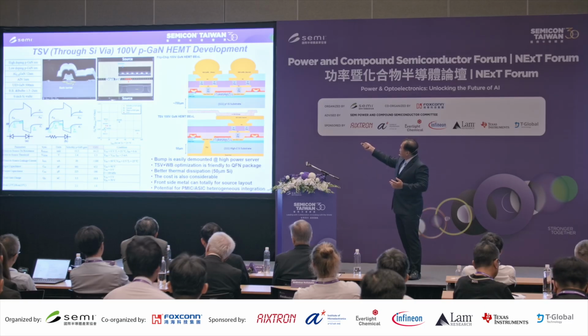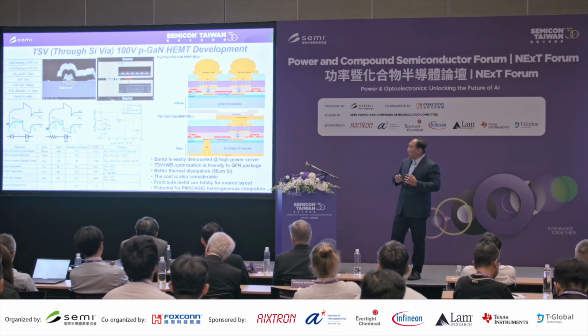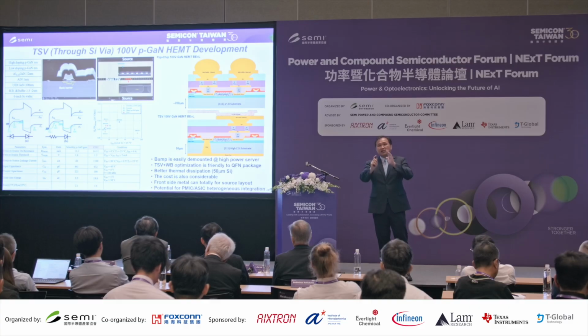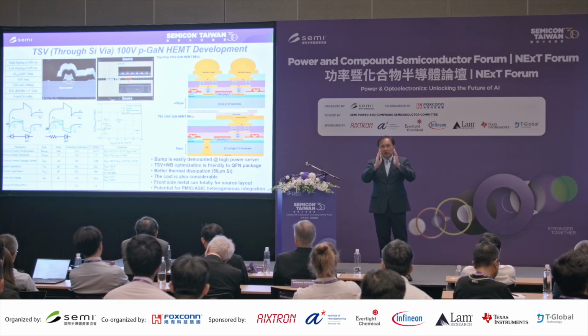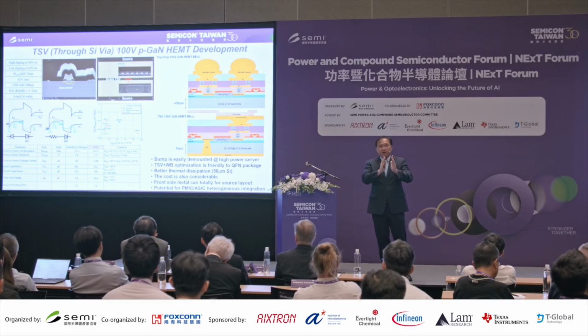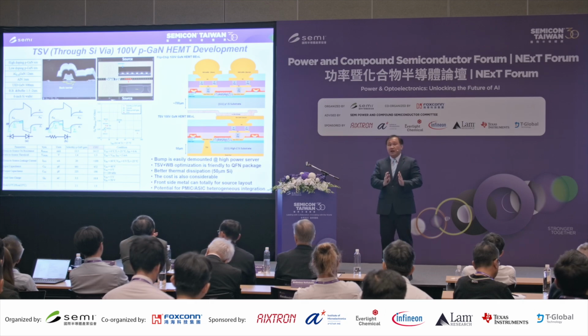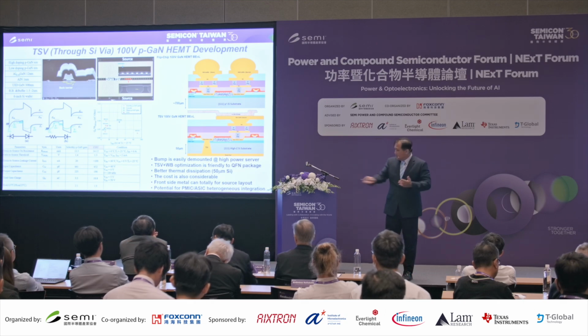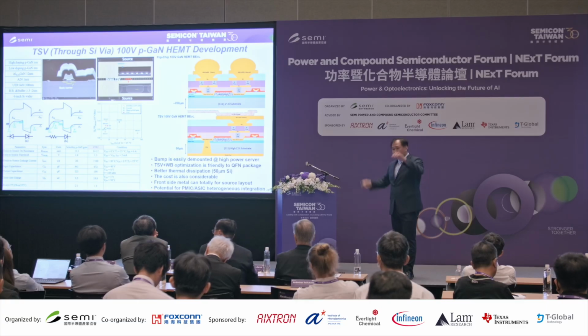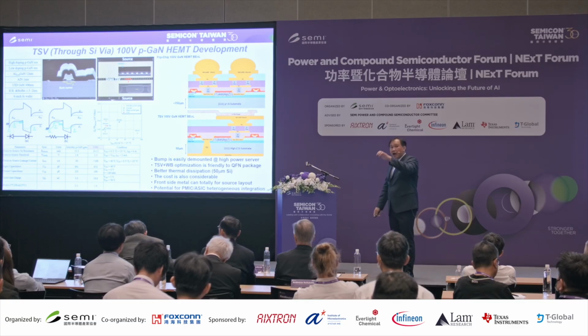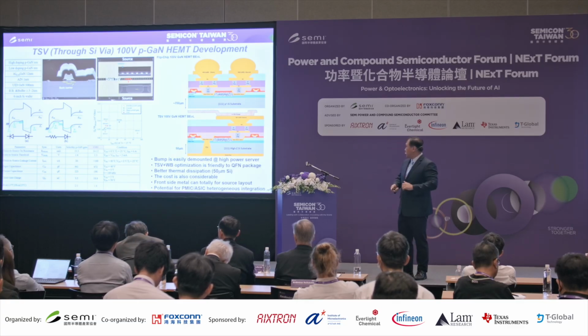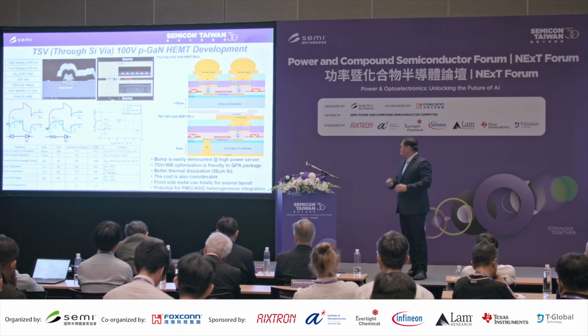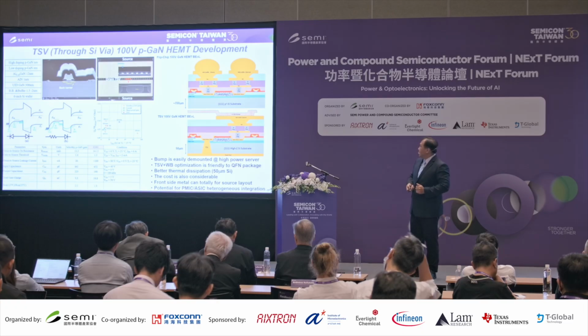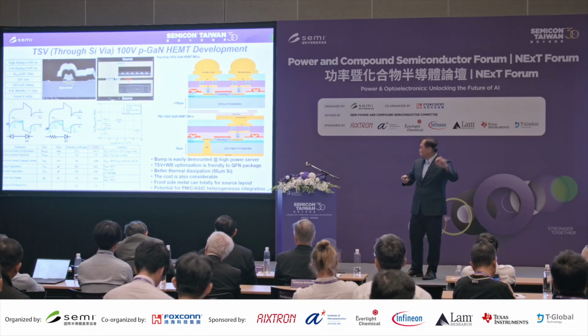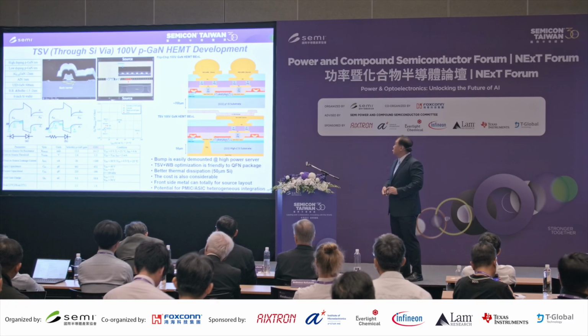and for the traditional 100 volt gallium nitride device, you have a lot of back end. A complicated back end means very much parasitic effect. But for our device, the drain side is on the backside metal, and the source side, you can just leverage the silicon carbide device, just use the copper clip to do the package. The cost is also considerable, and the front side metal can totally follow the source layout. Okay. And of course, the wafer was thinned down to 50 micron. It's very good for thermal dissipation.